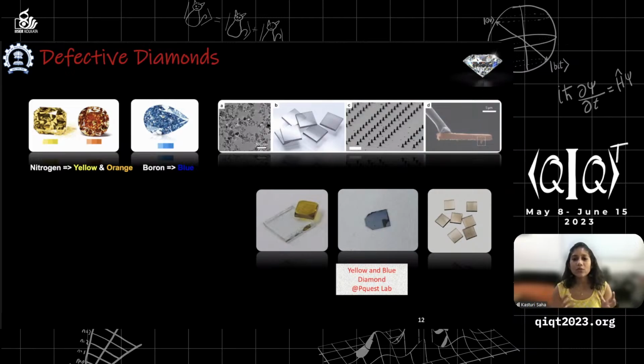As we know, nitrogen is highly prevalent in Earth's atmosphere, almost 78% or so is nitrogen everywhere. So when the diamond is grown, nitrogen can seep into the lattice structure of the diamond, and that gives it a bright yellow color. You similarly can have an orange color depending on the concentration of the nitrogen. And if you have boron, which is also there in the Earth's crust, it can seep in and gives you a bright blue color.